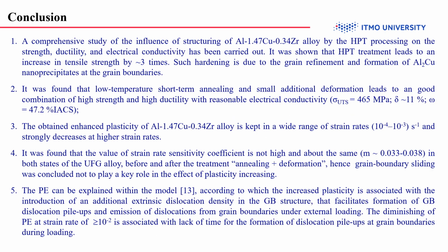Summarizing my talk, a comprehensive study of the influence of structuring of the aluminum copper zirconium alloy by HPT processing on the strength, ductility, and electrical conductivity has been carried out. It was shown that HPT treatment leads to an increase in tensile strength by 3 times. Such hardening is due to the grain refinement and formation of copper-containing nanoprecipitates at the grain boundaries. It was found that low temperature short-term annealing and small additional deformation lead to a good combination of high strength and high ductility with reasonable electrical conductivity.